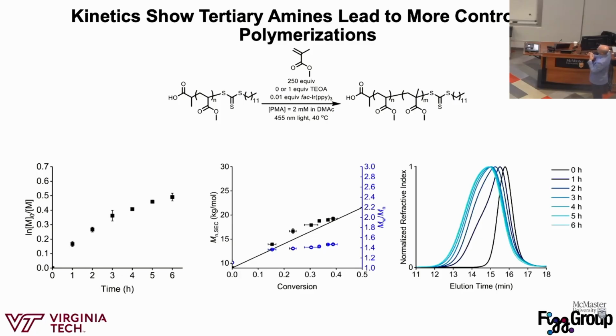So now we can better predict the molecular weight of these chain extensions. This is a pseudo first order kinetics plot. We want it to be linear, and if we see deviations from linearity, that means that we're losing radical concentrations. So we're getting termination events after about 3 hours. But it's linear for the first 3 hours, so that's actually pretty interesting to us.